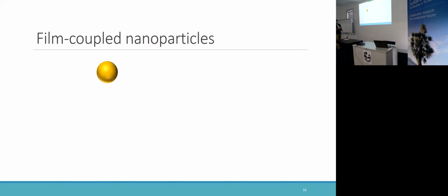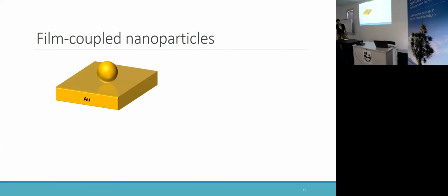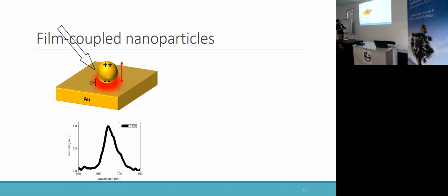Another way to modify the optical properties is to break the symmetry of the dielectric environment. For example, we can introduce a gold film or gold mirror at the bottom of the nanosphere. In this case, the symmetry of the dielectric environment along the Z axis is broken. When a beam of light shines here, the incident light can be highly concentrated and resonating at the gap between the nanoparticle and the gold film.